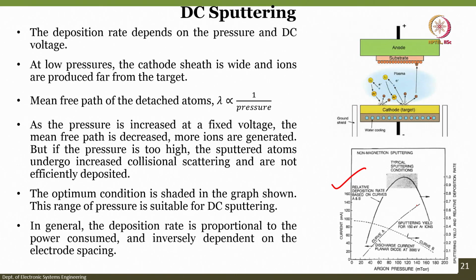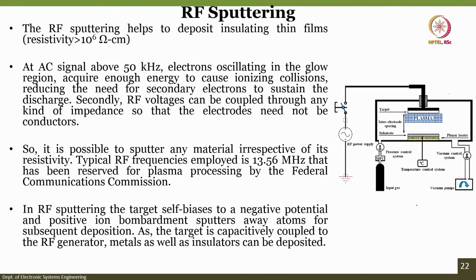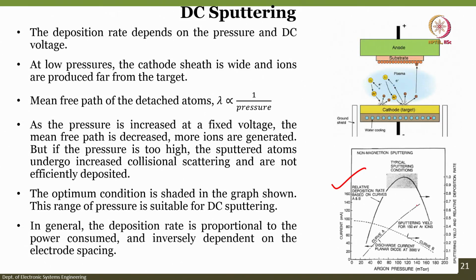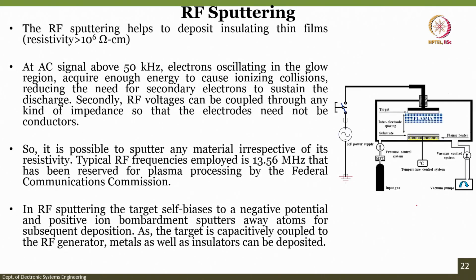Now, from DC sputtering, if I want to go to RF sputtering, then RF sputtering helps to deposit insulating thin films. In DC sputtering, there is a difficulty of depositing insulators, but in RF you can very easily do that. So, for films like silicon nitride and silicon dioxide, you can use RF sputtering. In RF sputtering,